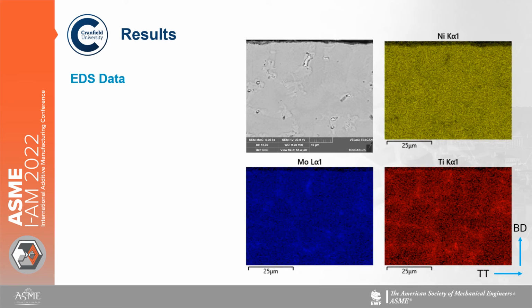So if we look at the EDS data of this sample, you can see already the depletion of nickel in this formed phase here, this brightly coloured one, and you can see the concentration of molybdenum in that phase as well. And then our darker coloured phases, which are these ones, you can see are actually rich in titanium.